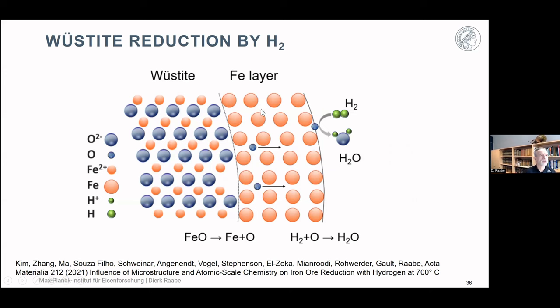Here you see a schematic picture. So when this is your dense iron layer, the first reaction was, of course, at the surface, that is trivial. But then you have the oxygen getting rid of its two electrons, using them to reduce the iron. The iron would relax towards the inner surface, so the iron grows from right to left. And the oxygen then, as an atom, sees the gradient in the chemical potential close to the next nearest surface and will diffuse through that iron layer to react at the next nearest surface to form water.